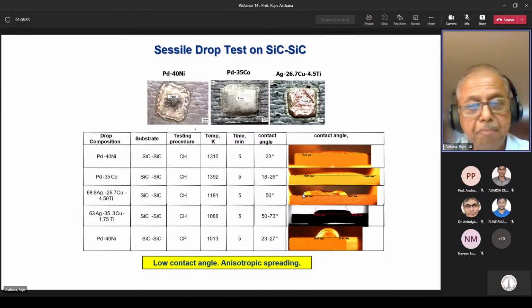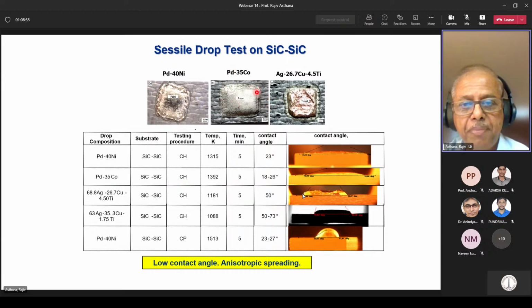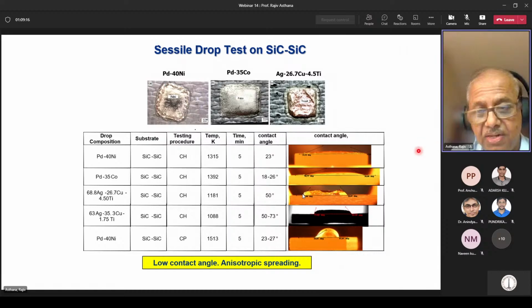Some of the tests we did were on composites because my interest has been in joining ceramic composites to alloys. And obviously, because of the inhomogeneous surface of ceramic composites, even after polishing and cleaning, you see that the spreading process is not very homogeneous or uniform. And the droplets spread anisotropically, not in a nice circular fashion, but in a more anisotropic fashion. So again, we measured contact angles by contact heating. Also, some capillary purification methods were used. In most cases, we see a good wetting, mainly because our brazes were all reactive brazes. But from a fundamental point of view, none of these angles is actually the Young contact angle. It is, again, a practical indicator.